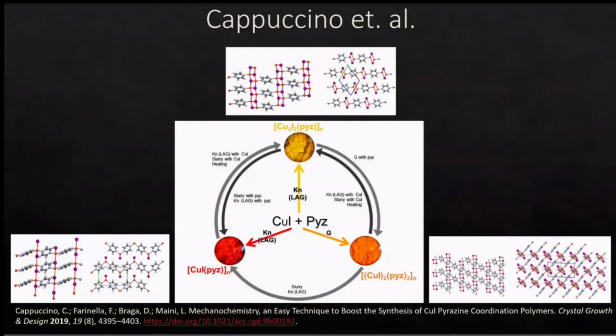In doing research for this presentation and for this paper, we ran across another group who had actually looked at this exact same system and had found that they could make the red and yellow polymorphs by liquid-assisted grinding in a ball mill. And so this group was able to make both of these polymorphs and do so much faster and with less energy and less solvent than the original synthesis pathway.